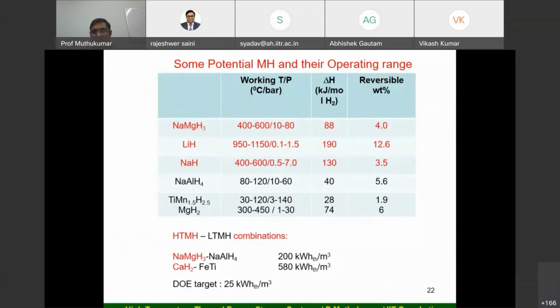Again, here you can see this is the working temperature range for magnesium. These are the kind of complex hydrides, but these hydrides are still in the R&D stage, and there are issues associated with them, mainly the cyclic stability. But people are working on it, and most likely they will get some breakthrough. But what I'm trying to say here is that these materials have very high storage density compared to the other hydrides.